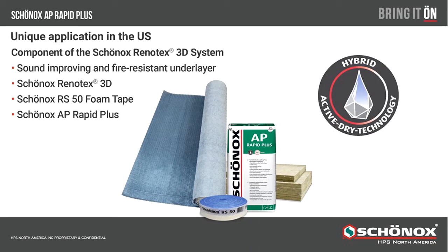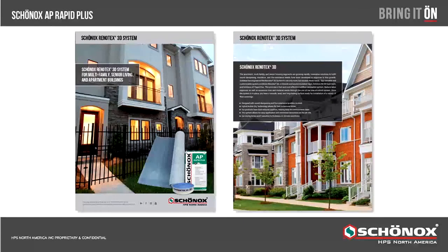We can put that full system in at a reduced thickness of only 1 inch versus some of the traditional systems you're seeing in multifamily use today. So this is going to be very important for new construction. This gives us a very low life cycle cost because of the durability and the versatility of the system. No longer are we putting in traditional systems that will be around 2,000 PSI strength. This is going to be upwards of 6,000 PSI compressive. It gives you very high versatility on the flexibility as well.